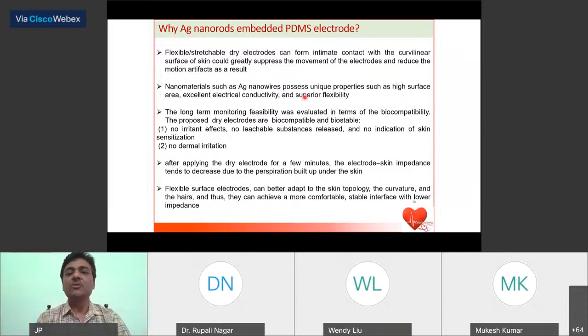Other than that, because of the increase in the contact area, the overall skin-electrode impedance in the case of our electrode is much lower compared to the conventional one, which is one of the biggest advantages. Moreover, this material is biocompatible, and we also found that with continuous use it does not produce any irritant effect or dermatitis. Moreover, this is dry. Just by controlling the PDMS and curing agent amount, we have made the top layer a little sticky, so it doesn't need any glue.